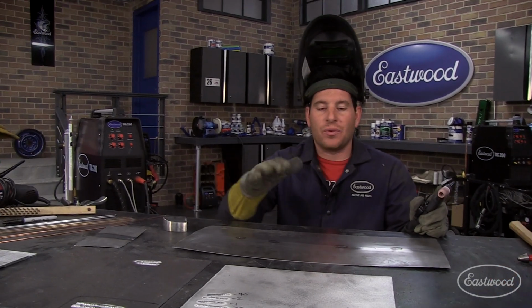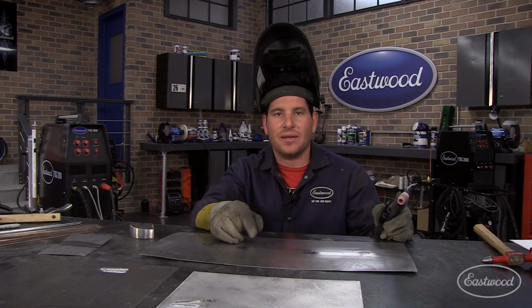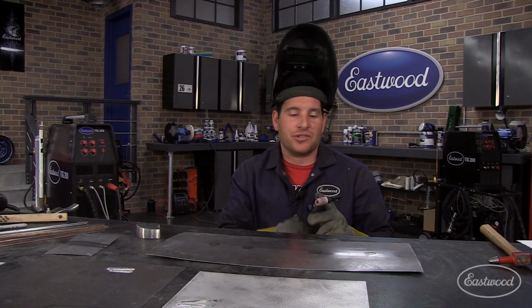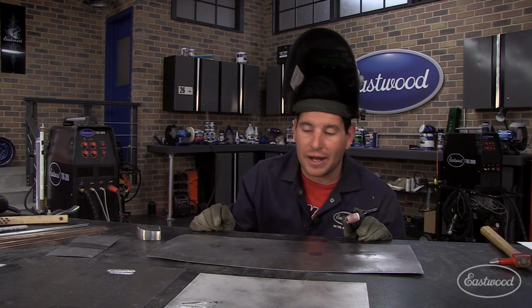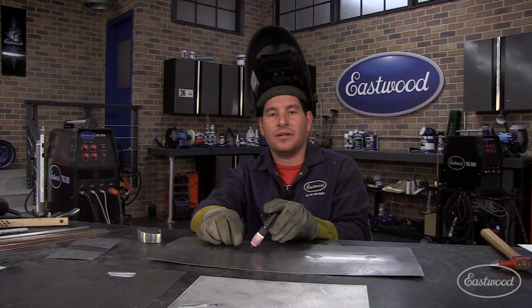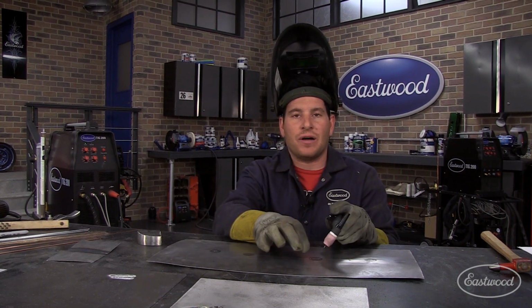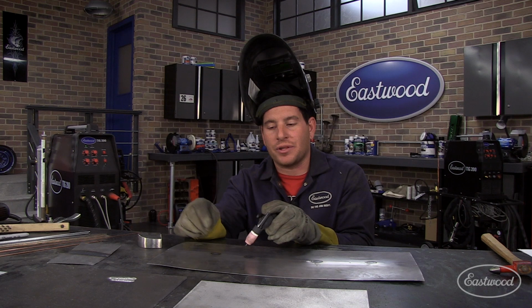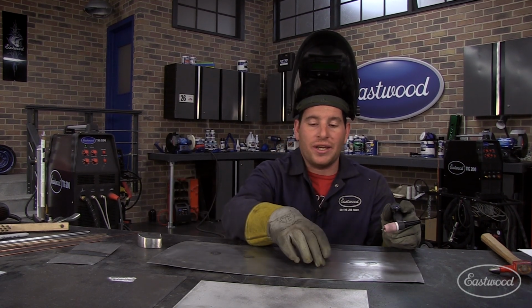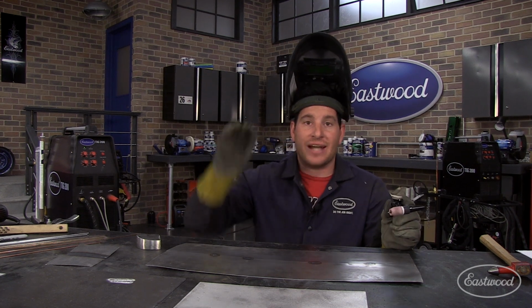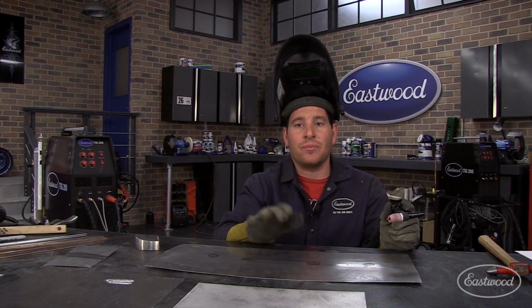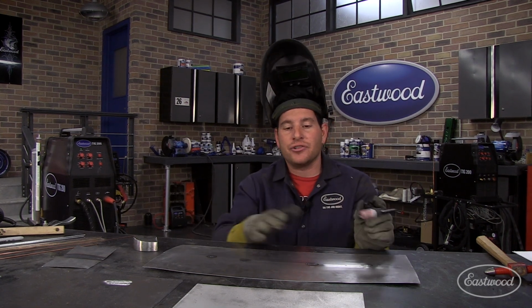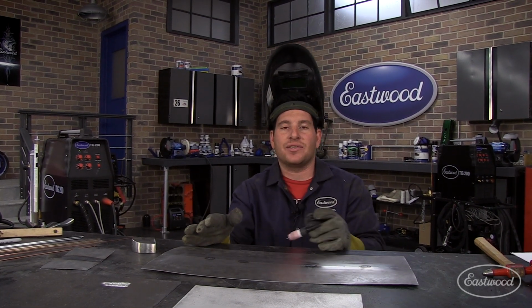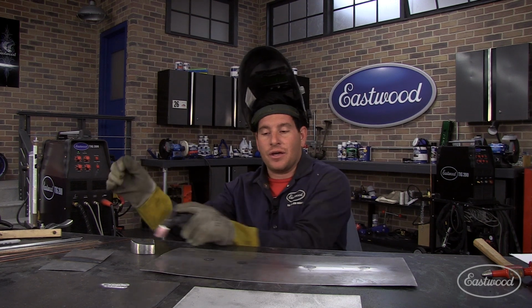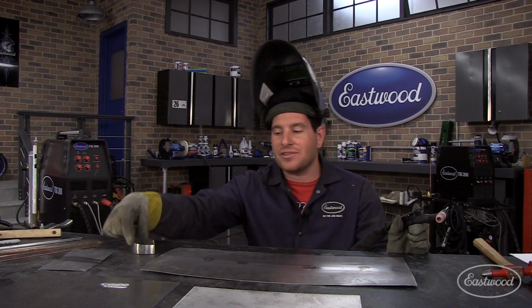The reason that you see the waviness is because it's inconsistent heat between each weld. So unless you're a robot or dang near a robot, it's very difficult to get this weld exactly the same heat as this weld. You know, you might have a time where you dab a little slower than another time. That's going to be more heat here than there, which is going to cause more shrinkage. That's your highs and lows. It's going to get more hot in one area and shrink more than another area. So you have to hammer it out to get it all flat, which requires hammering in some areas more than another. Perfect world, if you're a really good welder, you could sit here and go all the way across real fast, keep the heat exactly the same across the panel.